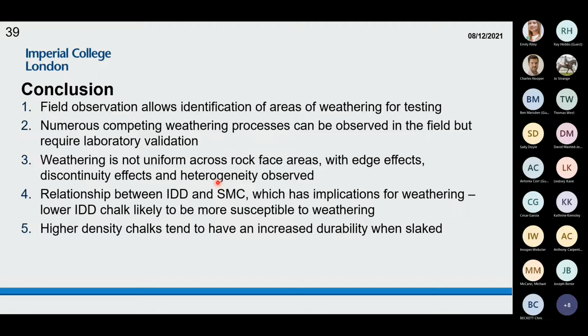Weathering's not uniform across rock face areas. You get a lot of edge effects, discontinuity effects, and there is heterogeneity observed. These are what was observed in the quadrats, in different values and different changes of UCS. There's a significant relationship between intact density and saturated moisture content, and this has implications for weathering and even identification of weathering.